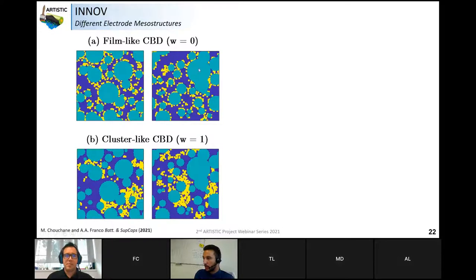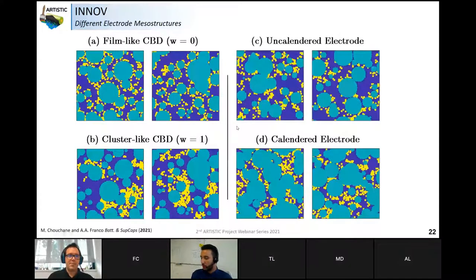But you can also choose with the same active material structure to have something like agglomerate, which will leave much more active surface area on your particles, and also tends to have clusters of carbon binder domain. You could also try to simulate the calendaring effect, meaning in an uncalendered electrode, you will usually have more porosity and maybe more distance between your active material particles. And as you calender, you will reduce your porosity and also bring closer your active material particles. So through this stochastic generation algorithm, you can really control these two aspects and somehow mimic the calendaring effect on electrodes.